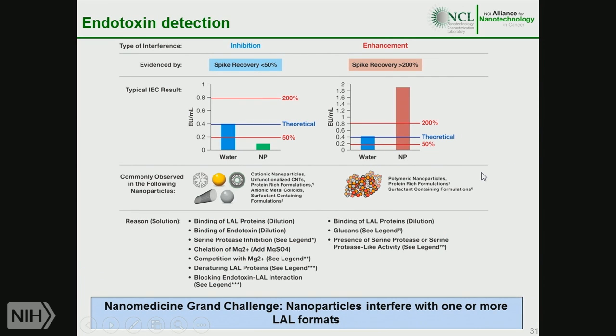The grand challenge in nanomedicine is accurate detection of endotoxin, because many nanoparticles interfere with one or more LAL formats. What you see on this slide are two main types of interference. One is called inhibition, which is defined as spike recovery less than 50%, and another type is called enhancement, which is determined by spike recovery over 200%. What does it mean? Look at this data. This is endotoxin spiked in water. Blue line shows the theoretical value. Theoretical means that we spiked 0.4 EU per milliliter of water, and we recovered almost 100%, right? This is accurate detection. Same in this case.